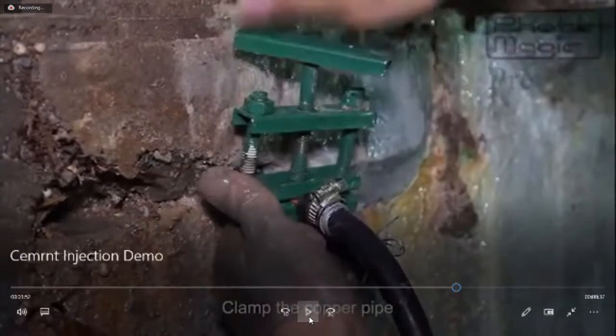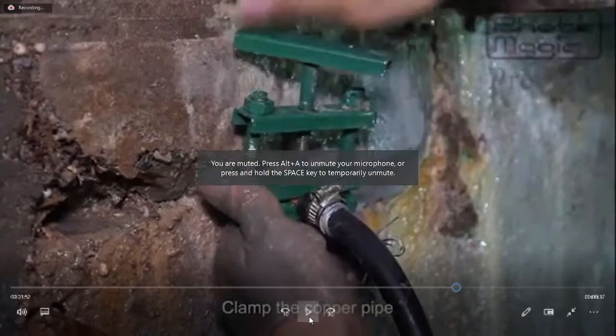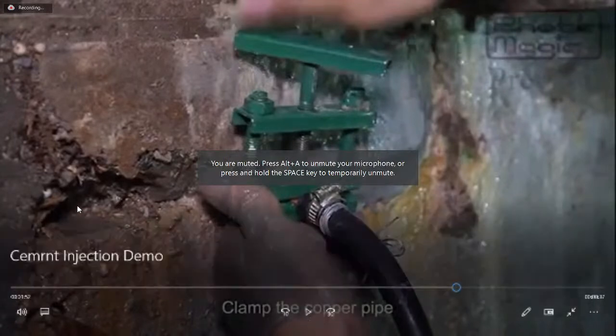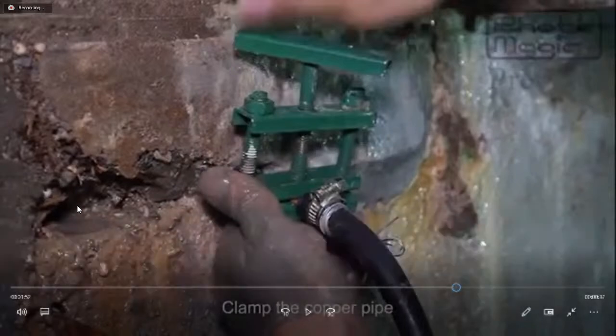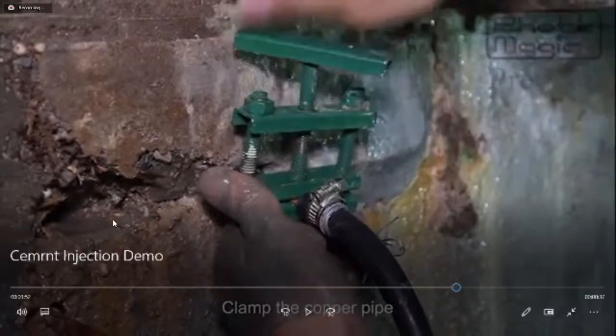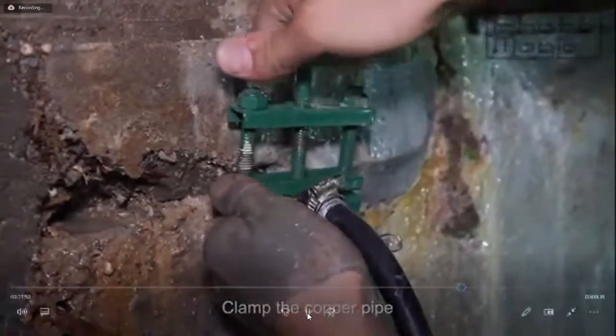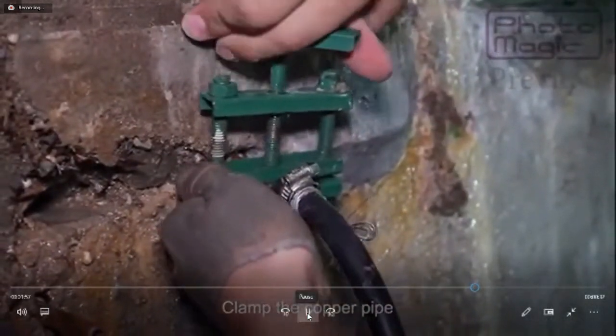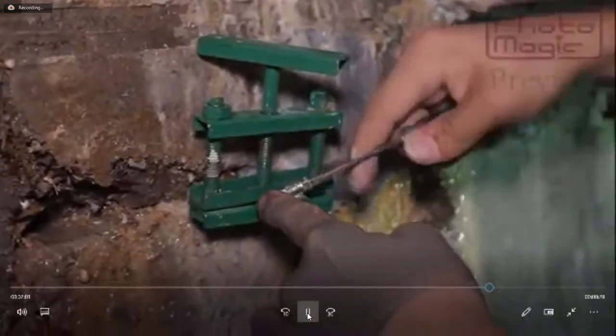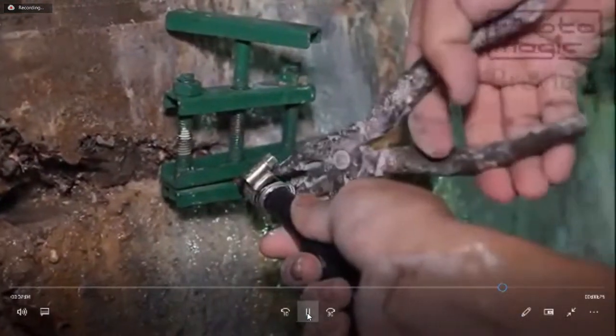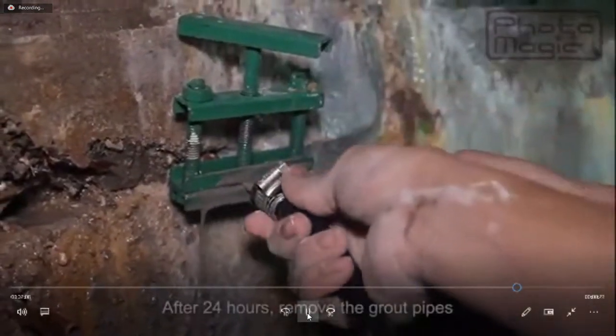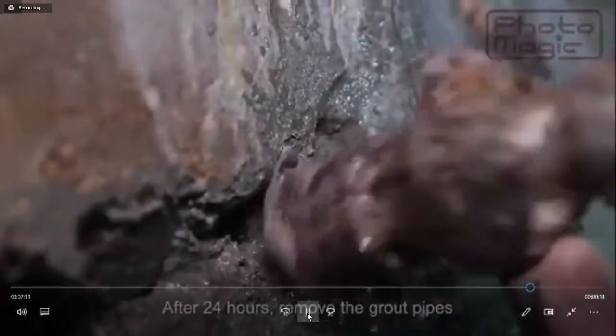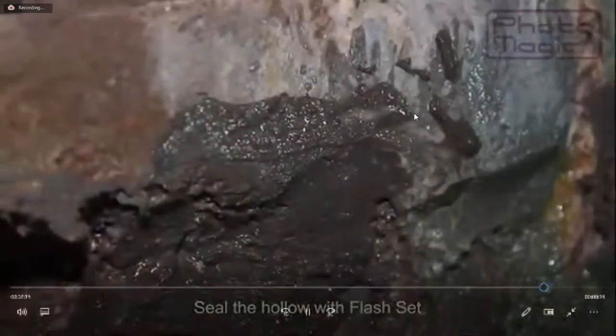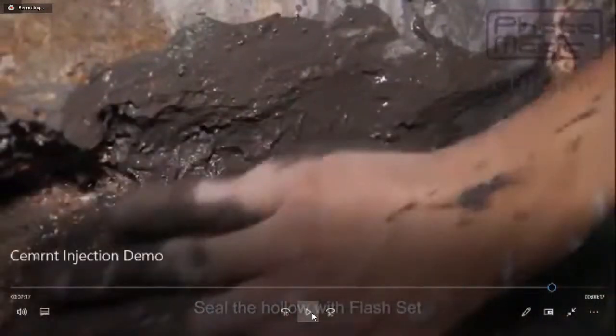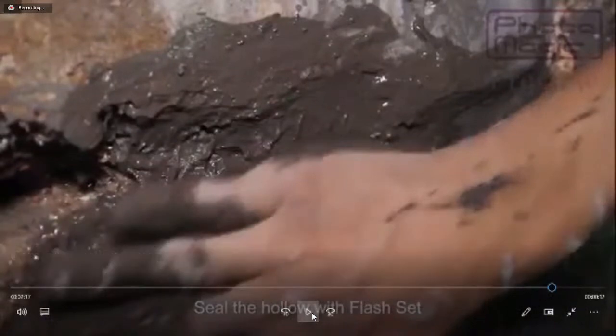So now with this pressure, the contractor is pushing this cement slurry into the concrete. This is a bad concrete. This is going inside the concrete and sealing the porosity in the concrete. After a particular pressure level has been achieved, they will stop this grouting and they will seal this hole. This way, they are sealing the holes so that the entire slurry goes inside the concrete. It sits there and water has been permanently stopped.